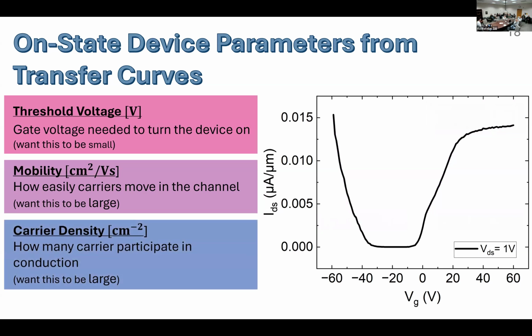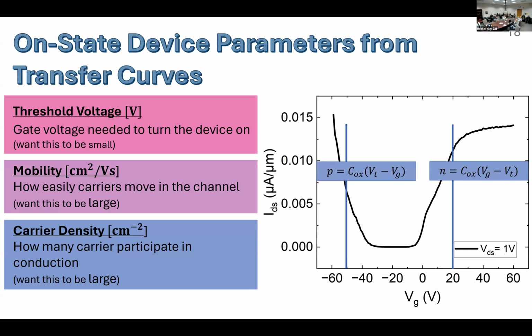Finally, another important key parameter that we can obtain from this graph is the carrier density. So how many carriers are participating in conduction in the on state? So we can do this by simply drawing a line across what gate voltage we want to look at. So in this case, I've drawn it for 20 volts and minus 50 volts. They have to be above the threshold voltage, of course, because we're looking at the on state. And simply by looking at the equation of the charge for a parallel plate capacitor, we can obtain the charge density for holes and electrons by plugging in this value, the threshold voltage, the oxide capacitance, and then we'll get a value for the carrier density.